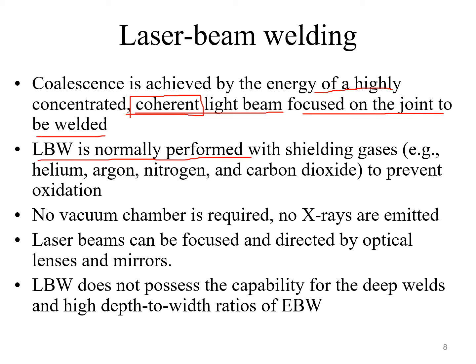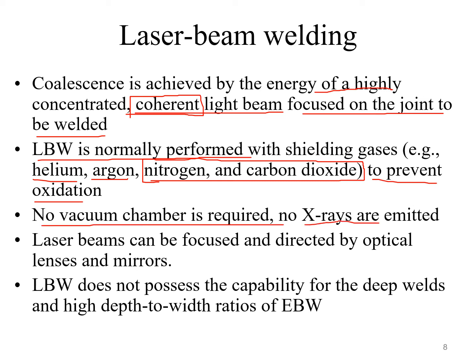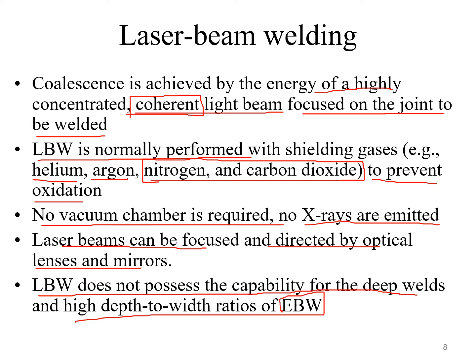LBW is normally performed with shielding gases, as for example helium is inert, argon inert, nitrogen and carbon dioxide, these are not inert, to prevent oxidation. No vacuum chamber is required, no X-rays are emitted. Laser beams can be focused and directed by optical lenses and mirrors. LBW does not possess the capability for deep welds and high depth to width ratio of EBW. That means compared to electron beam, the laser beam does not possess the capability of deep welds. The depth of penetration is not high.